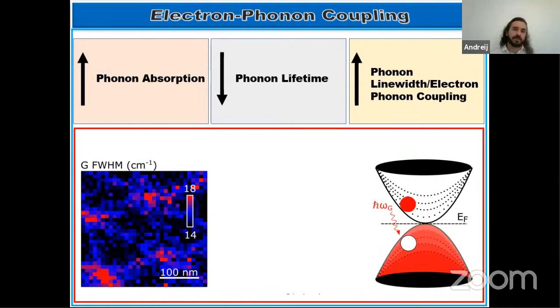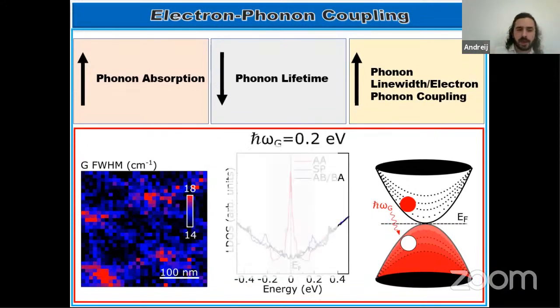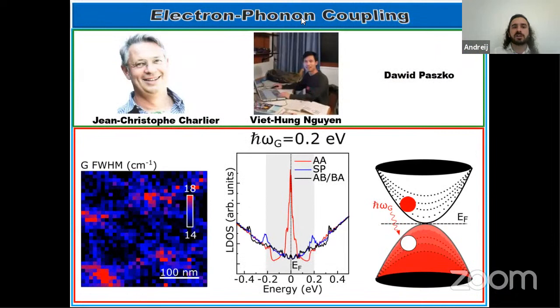And when the phonon line width increases, the electron-phonon coupling increases as well. And this is just a simple picture. And we asked our collaborators from Jean Charlier's group to calculate the local electronic density of states for the rTBG at the AA, SP, and ABBA sites. And I marked here a region in gray where G phonons can mediate excitations and can do transitions, okay?